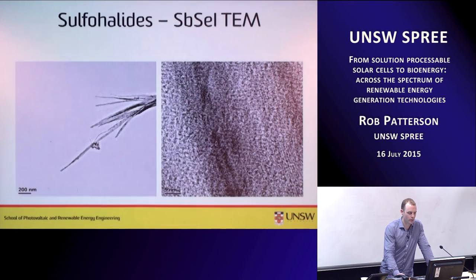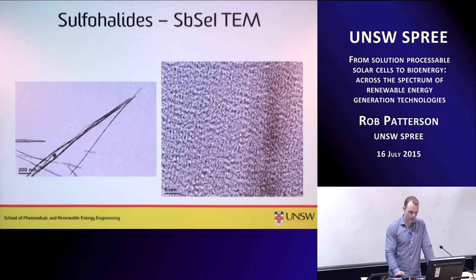Here's some TEM. So you can see that we have these nanowires. They're about maybe 20 to 50 nanometers in diameter, and they like to coalesce into bigger nanowires. And if you squint at this, you know, the next one's a little bit better, you can see fringes. So we should have some crystallinity in our nanowires. This is what's expected. And here you can see a full nanowire. So you can see they're quite long. The aspect ratio is quite high. We have maybe over a micron in length for 20 to 50 nanometers in diameter.